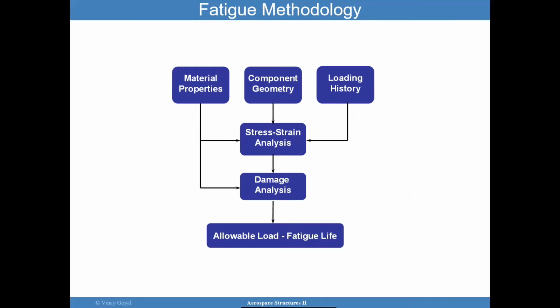The fatigue methodology typically starts with really understanding the loading history provided, the component geometry, and material properties. Once you have that and you have defined the stress-strain curves for the materials, then you can go into damage analysis using the service history, or the service life of the component, with the component geometry and the material properties. You can then use that information together with the fatigue data, and with those two together, you can determine fatigue life.